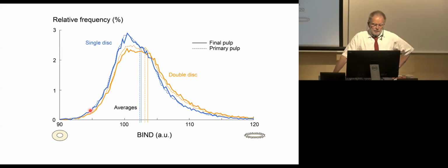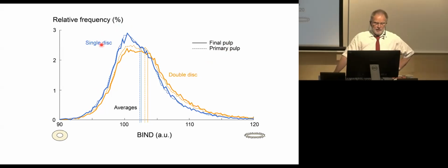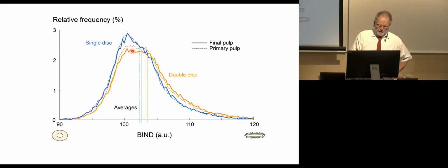And you can see the dotted lines here. They are very close to the primary, to the final pulp. So it's just on the final pulp, it's a little bit more energy added in the process. But even more interesting is that you can see they are different here. The single disc refiners and double disc refiner, that gives another different character of a pulp. And it has been known earlier, but it's also illustrated in these distributions. So it's a way to illustrate the distribution.